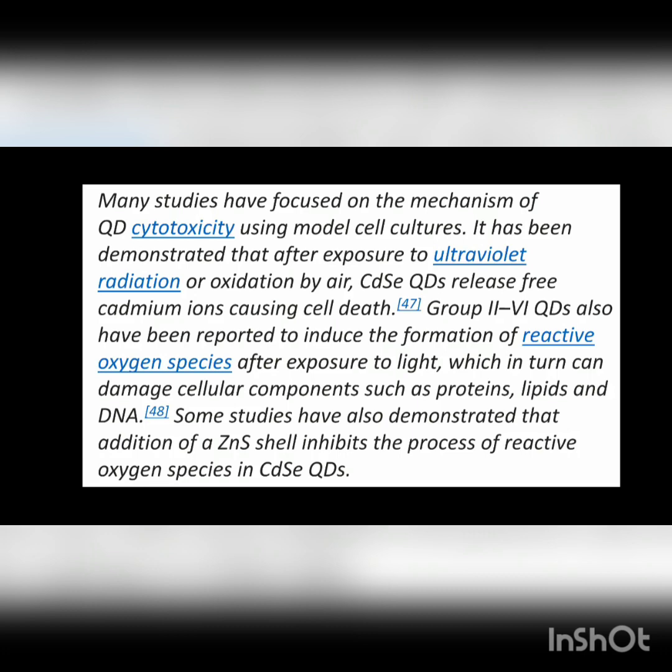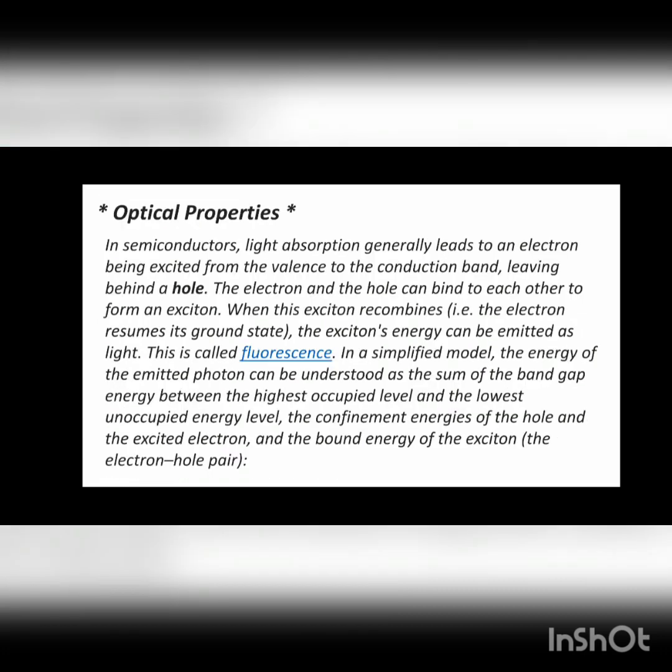Group 2 and Group 6 quantum dots also have been reported to induce the formation of reactive oxygen species after exposure to light, which in turn can damage cellular components such as proteins, lipids, and DNA. Some studies have also demonstrated that addition of a ZnS shell inhibits the process of reactive oxygen species formation and release of cadmium ions from quantum dots.